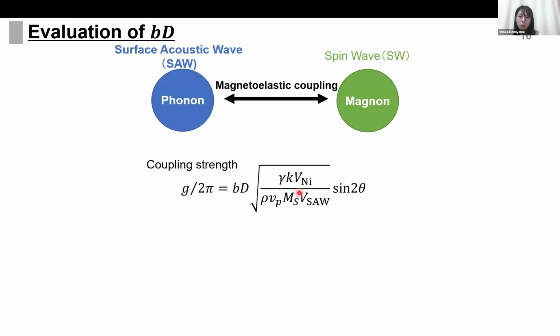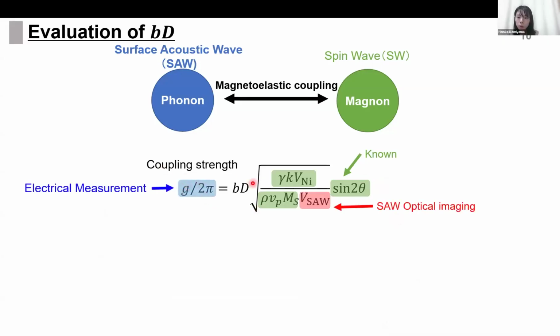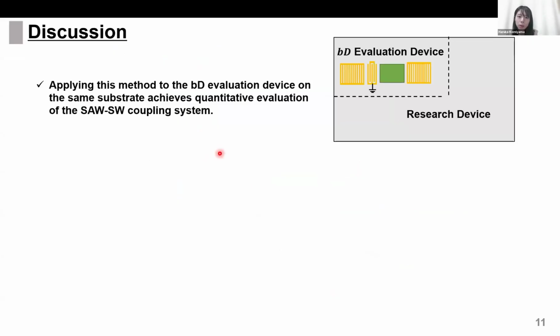The formula for G is shown here again. Substituting the literature values and experimental conditions into the green part, the value evaluated from the electrical measurement into the coupling strength G, and the value obtained from the optical measurement into the previously unknown surface acoustic wave mode volume VSAW, we obtain the constant BD as 8.1 times 10 to the fifth power joule per cubic meter. Quantitative evaluation of the coupling is possible by applying this method to a BD evaluation device on the same substrate as the device for research.